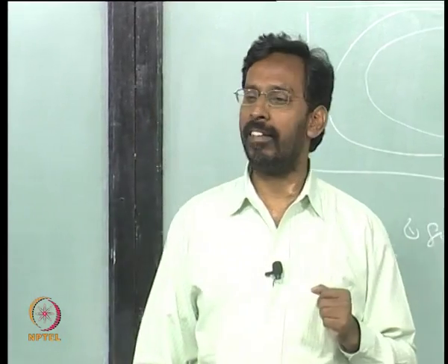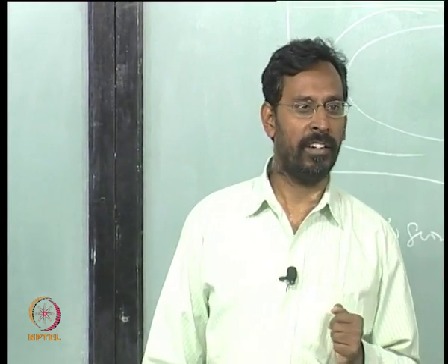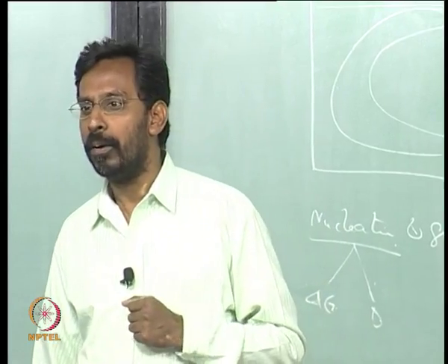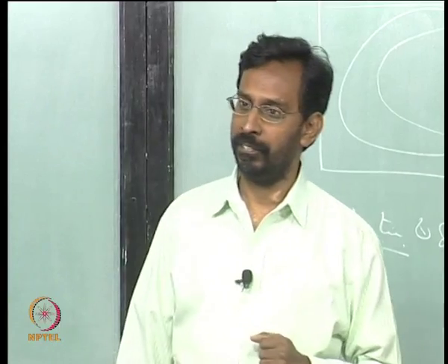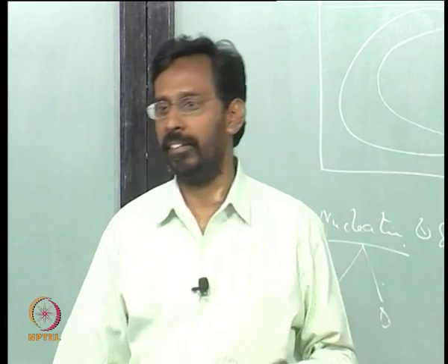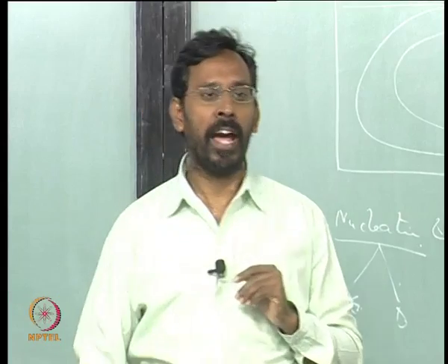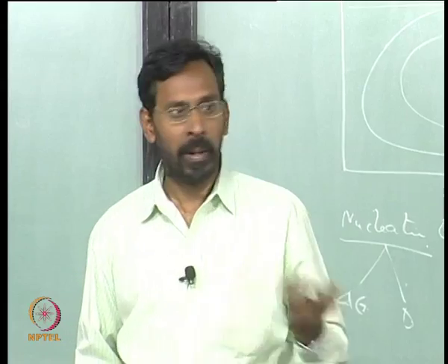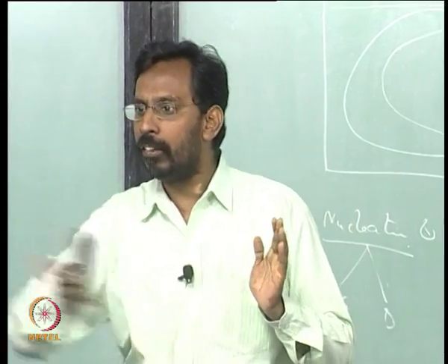You see this even in the case of steels, when you take a steel martensite and temper the martensite, I do not know how many of you remember, what is the phase that comes out during tempering? It is epsilon carbide, it is not the cementite which comes out. Why is that? Obviously epsilon carbide does not stay, if you do the tempering at higher temperature or for longer times, this epsilon carbide vanishes. Similarly the GP zones vanish, if you do aging for a longer time, GP zones turn to theta double prime, then theta prime, then finally the theta.